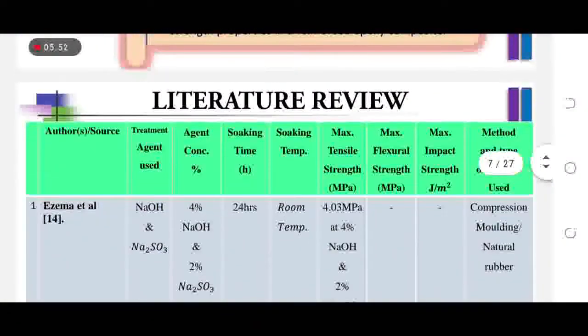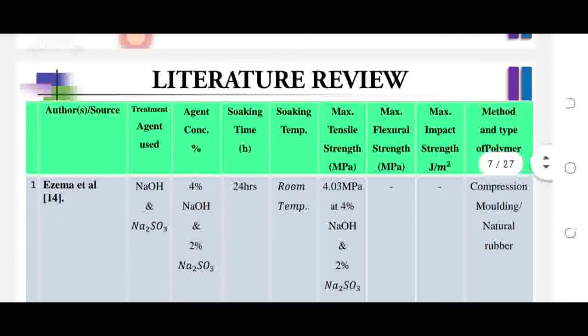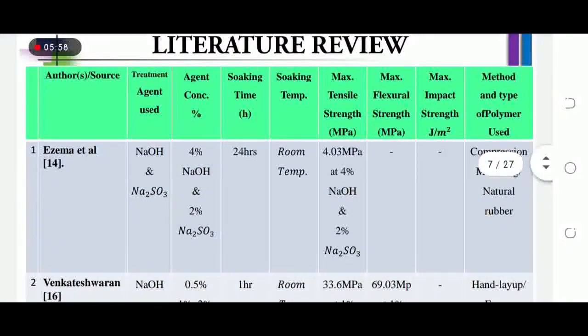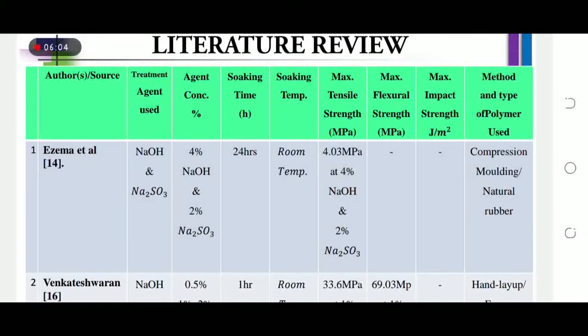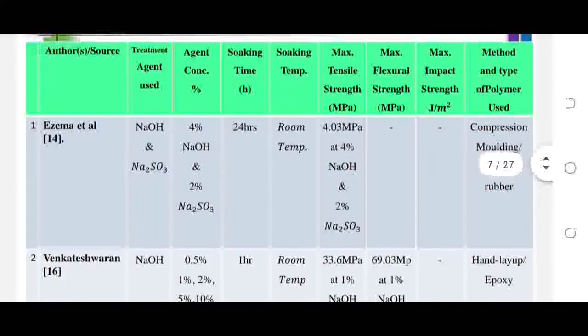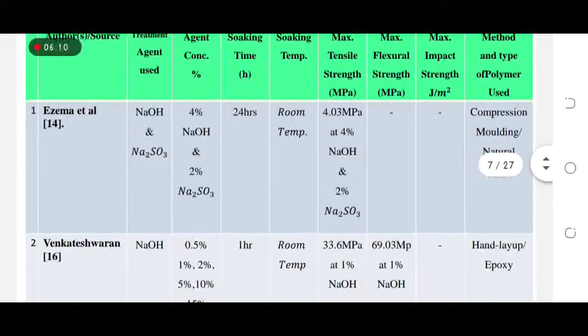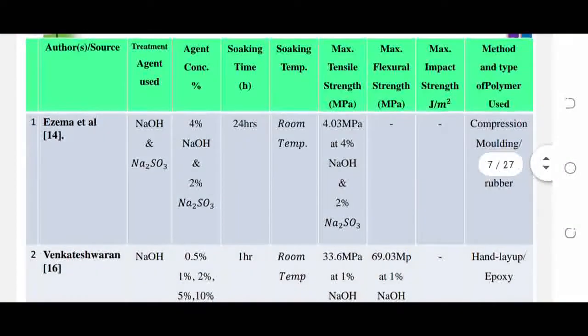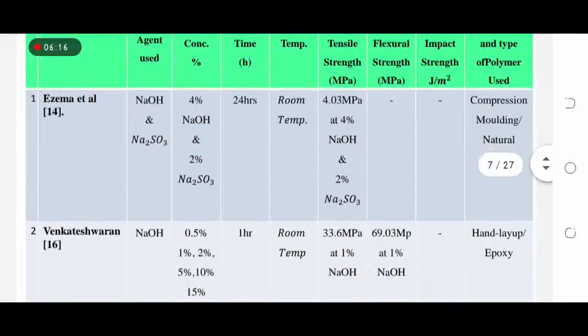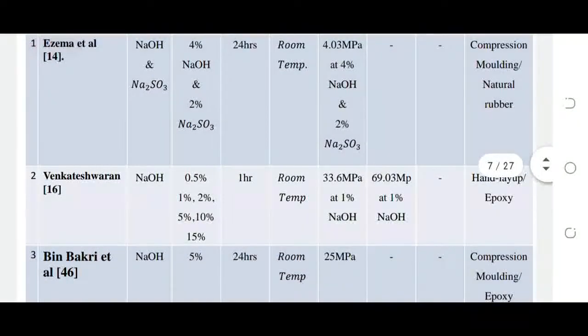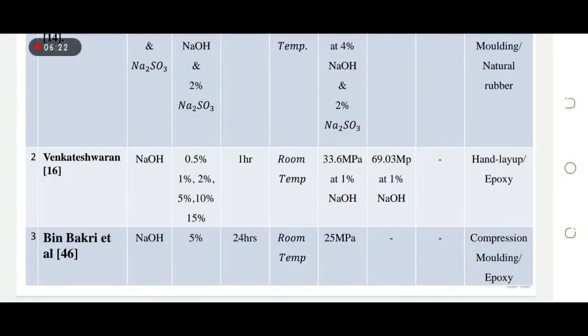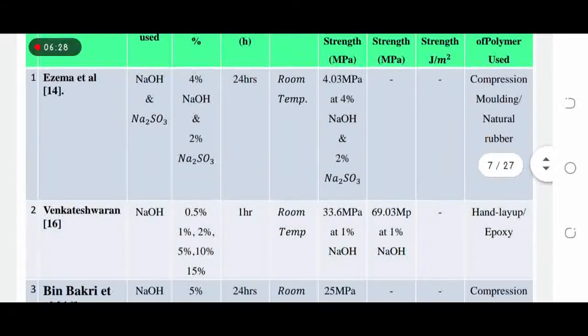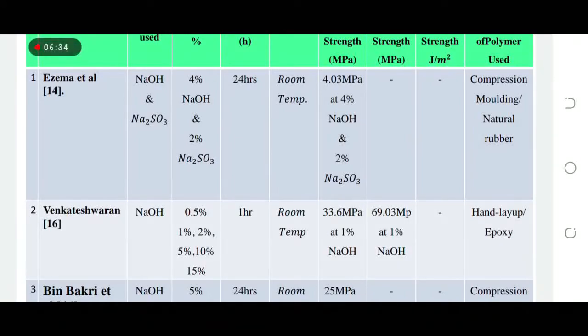So, literature review. In our literature review, we saw that Ezema et al. treated with sodium hydroxide and sodium sulphite for 24 hours with a concentration of 4% for sodium hydroxide and 2% for sodium sulphite. And this is the maximum they got, which is 4.0 megapascal at 4% and 2% of the reagents. Venkateshwaran also did the same thing, but here he treated with only sodium hydroxide, and at 1 hour he got 33.6 megapascal at 1% of the sodium hydroxide.